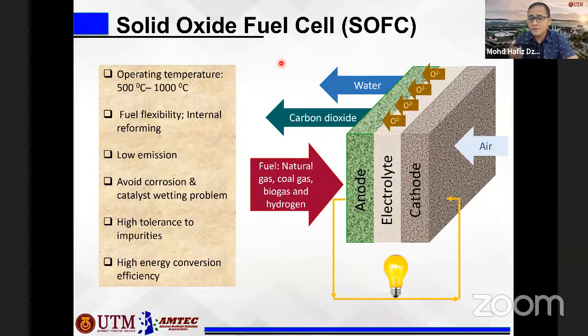And therefore you don't have to use a noble catalyst like platinum or any type of expensive catalyst like palladium as well. So by having solid oxide fuel cell, actually we can use cheaper catalyst because of the high temperature. Normally at this temperature, the catalytic activity is more efficient. And due to its high temperature as well, the fuel cell is flexible in fuel selection, meaning that you not only use hydrogen as the fuel, but you also can use natural gas, coal gas and biogas as the fuel. Many types of gases can be used as the fuel for the solid oxide fuel cell.